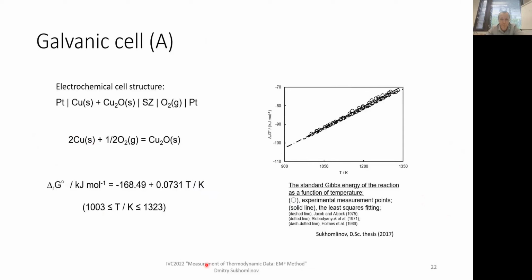So galvanic cell A, rather straightforward. Metallic copper and Cu2O, mixed, pressed into a pellet, stabilized zirconia solid electrolyte. Platinum can be used directly, not much corrosion at those temperatures, or not many side reactions, I probably should say, between electrode and lead wire were observed. And then a gaseous reference electrode. It was measured in a temperature range exceeding 300, so from 1000 to 1300 K. And it's been compared to some literature data, found to be in very good agreement with previous studies.